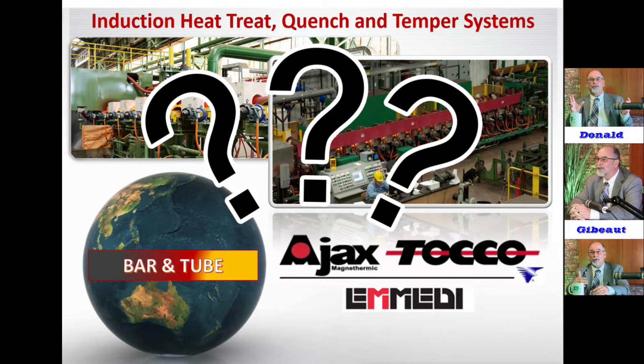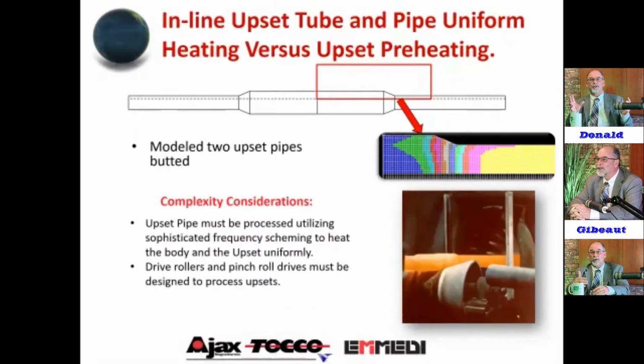And the API steel grades, yes, we can heat it. We do even stainless steel annealing and things, completely non-magnetic. But in API steel grades, the delicate grades, the P110 and the L80 has special parameters, and you spend a little time setting that up. But there is a open air and a higher temperature we get to. Now, we talked about those lines running, both lines are made for upset processing. The inline upset tubing for tube and pipe, you have a thicker wall in the upset. And then it tapers down and goes to the body.